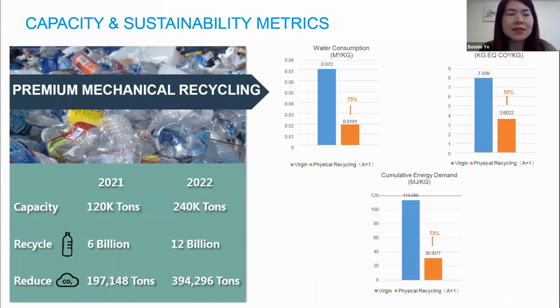Based on a third-party life cycle assessment report, Cyclone Recycle Yarn reduces 75% of water consumption, 55% of greenhouse effect, and 73% of cumulative energy consumption compared with the virgin yarn. You can see each kilogram of the recycled yarn reduces 4.3 kilograms of CO2. So with a capacity of 240,000 tons in 2022, we can recycle 12 billion waste bottles and reduce 394,000 tons of CO2 emission.